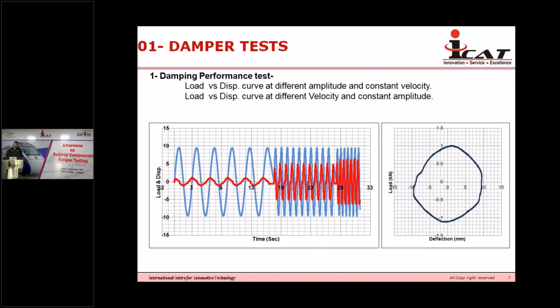There are two kinds of tests we perform. One is the damping performance test, which you can call a performance or characteristics test of a damper, and another is the fatigue test. In damping performance tests, we can conduct in 2 ways. One is we find the load versus deflection curve at different amplitudes and constant velocity. Another is a load versus deflection curve at different velocities and constant amplitude. As we know, damper forces are directly proportional to velocity. So if we change the velocity with constant amplitude, forces will be high, as you can see in this curve.